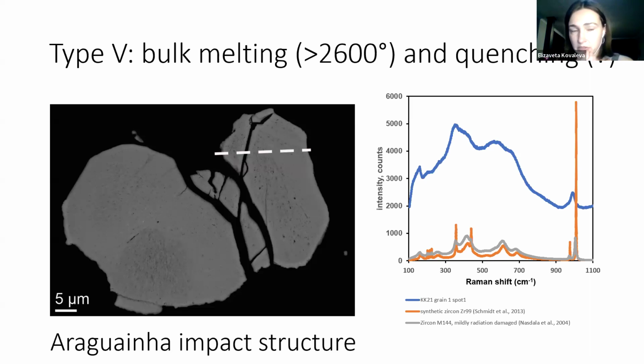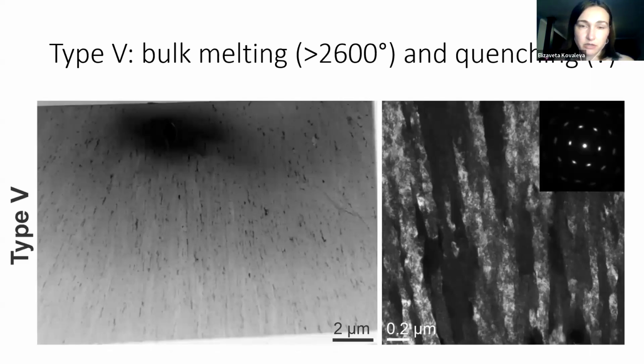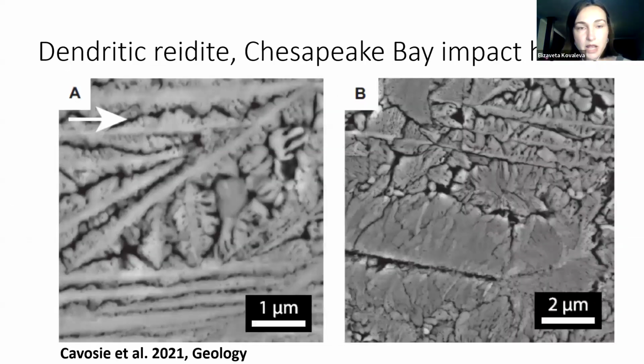We did Raman spectroscopy, which was just showing that it's a very damaged structure. And this is how it looks under transmission electron microscopy. Single crystal, long, elongated, alternating subgrains with approximately the same orientation. How it forms, I can only suggest bulk melting and very rapid quenching.